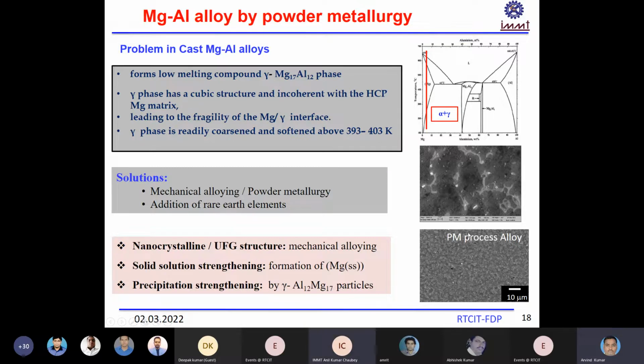In the powder metallurgy method, we are doing mechanical alloying and forming nanostructured ultrafine grains in this alloy, and then solid solution strengthening. Because of the mechanical alloying, you can increase the solubility limit of aluminum in magnesium, so that more and more aluminum goes into solid solution. So the aluminum forming the gamma phase will be very little. That's why you can reduce the gamma phase in this alloy.